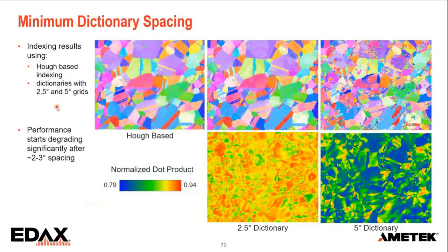We can go coarse, and here's just an example of that. This is the original Hough-based indexing and two examples for dictionary indexing. When we take a 2.5 degree dictionary, the patterns are similar enough that we can identify all the orientations. We see a little bit of colored jumps here. Those are just the intervals of the simulated patterns.